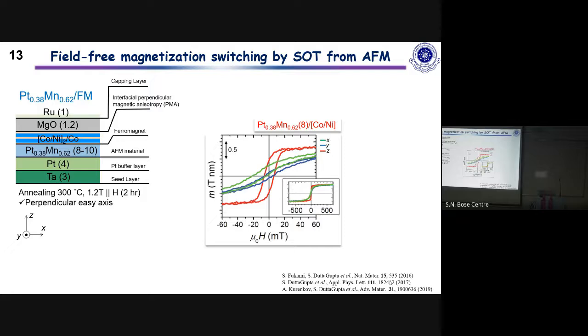I think these are very thin layers. In my understanding and experimental observations, this probably forms an alloy, because this is 0.3 to 0.4 nanometers, and this is 0.6 to 0.7 nanometers. Even when we do transmission electron microscopy, we cannot identify the individual layers because they are probably not even one monolayer. But I think they form an alloy. The only reason we use this cobalt nickel repetition is that it becomes easier to tune the magnetic anisotropy. Depending on the repetition and the number of stacks, you can control the anisotropy depending on your requirement.